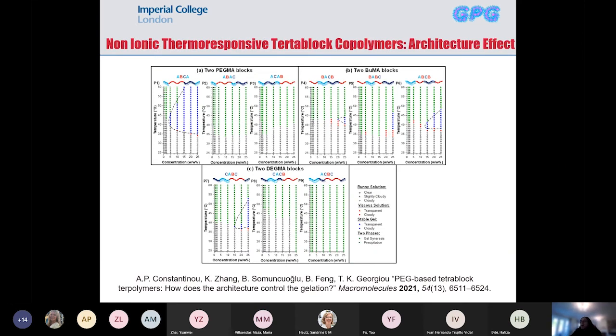Now, we did also investigate, with a new combination of monomers, if we change the architecture this time, whether we are going to find different results if we made, for example, tetrablocks. What we have seen is that we do have a promising architecture, but it's essentially the ABC structure with the A again repeated at the end. So it still includes the ABC structure. What is interesting is that it keeps the gel stable at higher temperatures, which may be desirable in some applications, but at the temperature that you do get gelation, the gel strength has increased compared to what we had before.